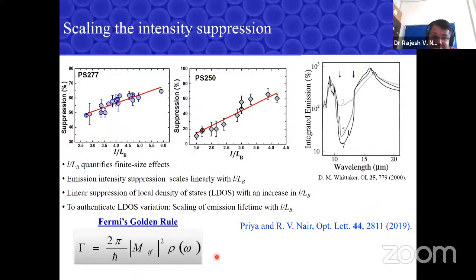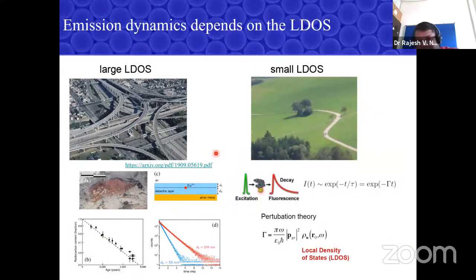So the referee's concern, which we were even aware of, is that the decay rate is proportional to the density of states. So if you want to say spontaneous emission is scalable, we actually have to do lifetime measurements, and show that instead of the intensity suppression, the lifetime should scale with that. So we did those measurements. And before I go to that, what is the LDOS? Probably if somebody is still not clear.